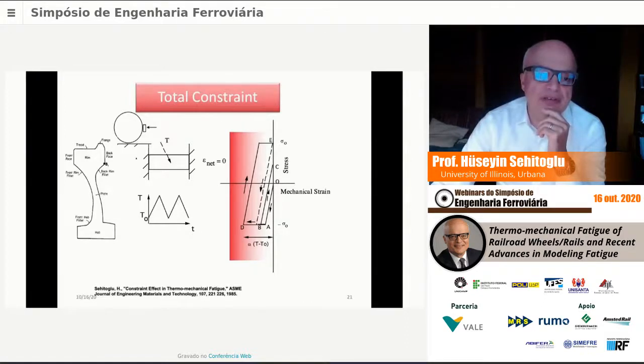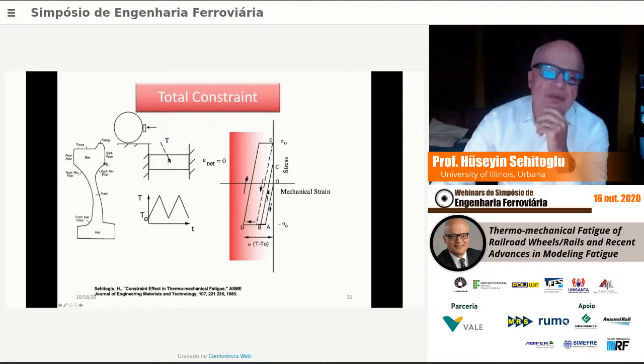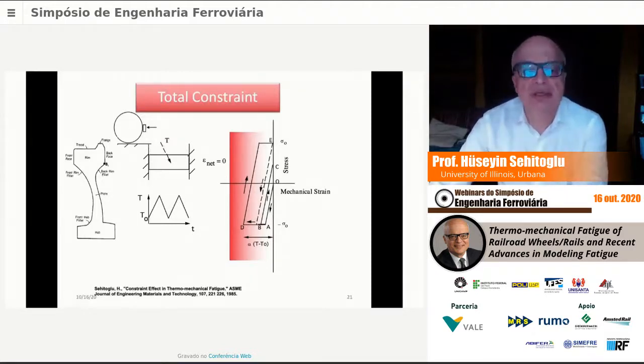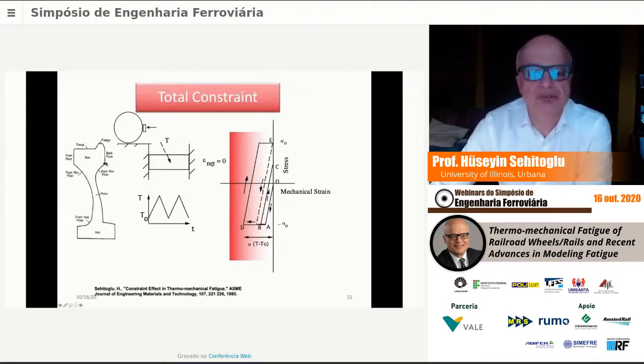If we look at this element of material here, we could think of it as constrained by the cooler material, right? So just the plate and the rim, the majority of the rim is pretty cold. So if you heat that region, it's almost completely constrained as a first approximation. So the net strain is zero, but the mechanical strain is not zero.